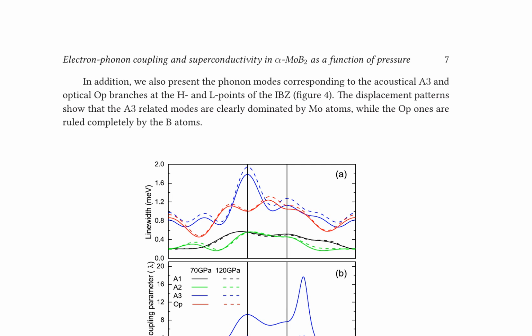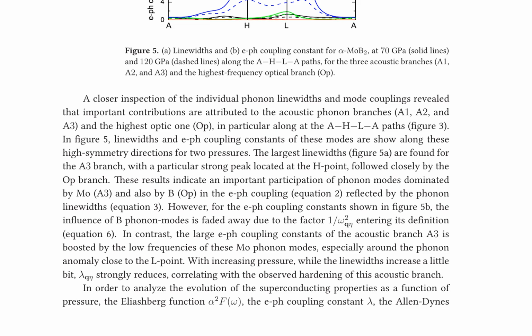branch, OP. The largest linewidths are found for the A3 branch, with a strong peak located at the H point, followed closely by the OP branch. These results indicate an important participation of phonon modes dominated by Mo, A3, and B, OP, in the EPH coupling. The EPH coupling constants, however, show a different trend, with the influence of B phonon modes fading away due to the factor 1 over omega squared q eta entering its definition.